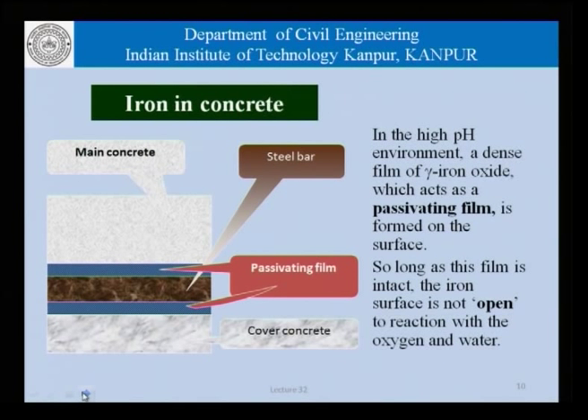We have seen this picture before, and it basically talks in terms of how iron in concrete is protected against corrosion. It is the high pH environment, and therefore, a dense film of gamma iron oxide, which acts as a passivating film, is formed on the surface as shown here. So long as this film is intact, the surface of the iron is not open to reaction with oxygen or water, which may be present in the cover concrete. But if this surface becomes available for attack, then the reinforcement is susceptible to corrosion.